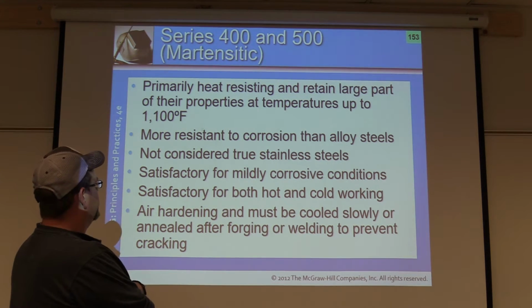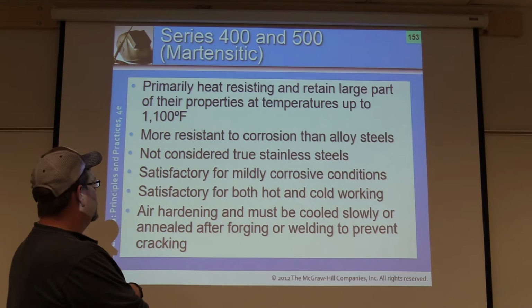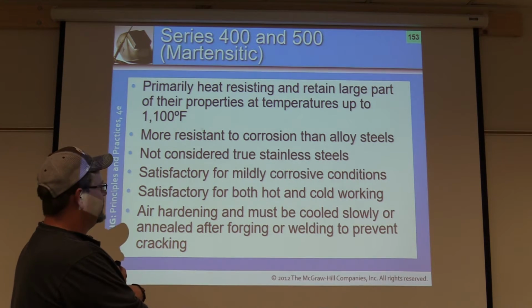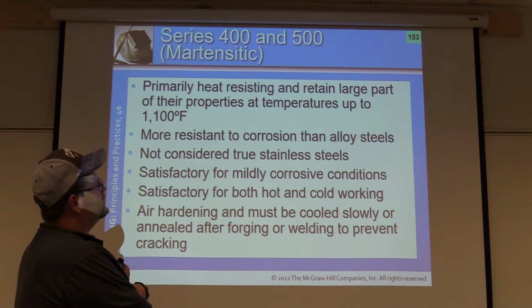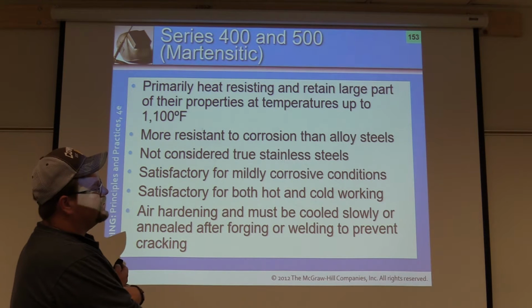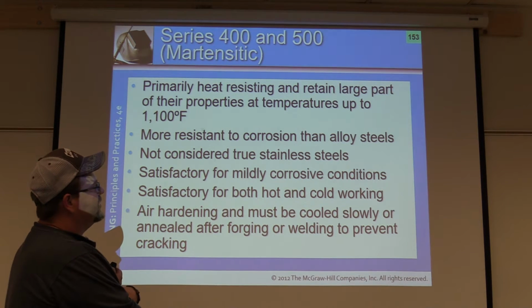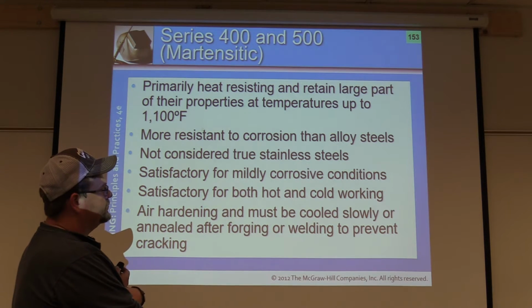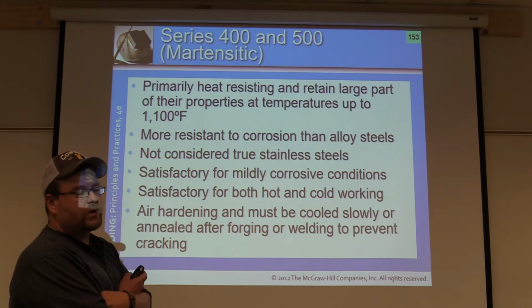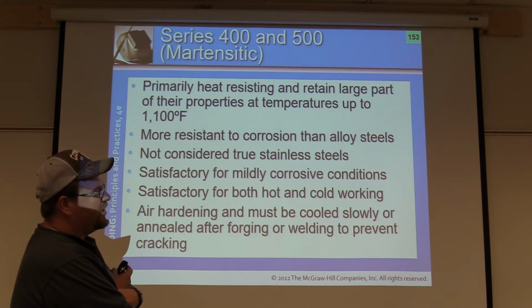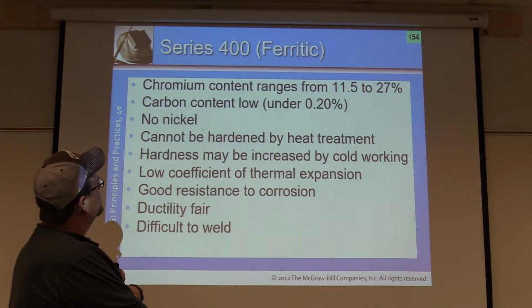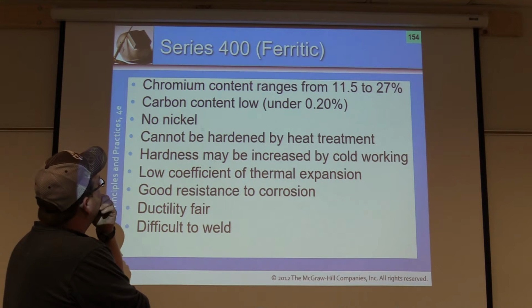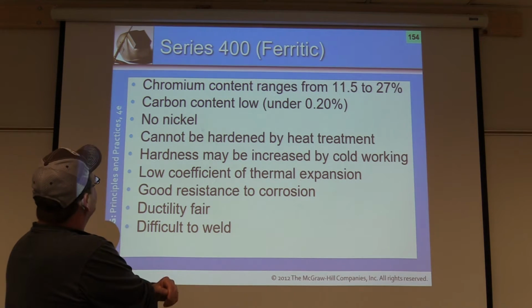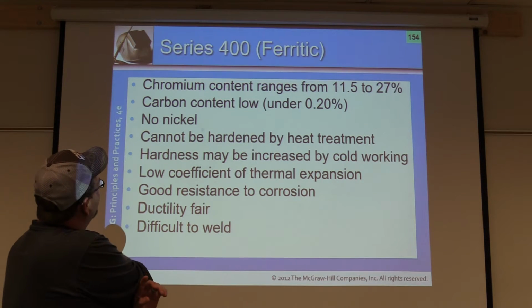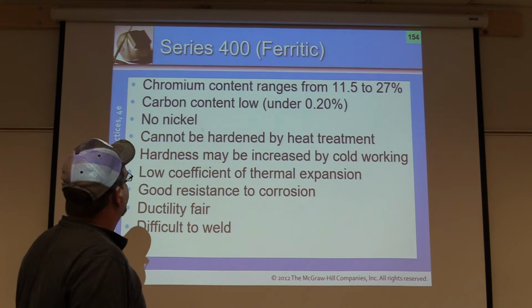Air hardened must be cooled slowly or annealed after forging or welding to prevent cracking. Highly susceptible to cracking, so you don't do a lot of it. If you do, make sure you're wrapping stuff up, using a torch to help bring it down nice and slow, or a weed burner if you don't have electric heat blankets or a furnace, and so forth, okay? 400 series. This is a good series of ferritic, so sometimes it can be magnetic, okay?